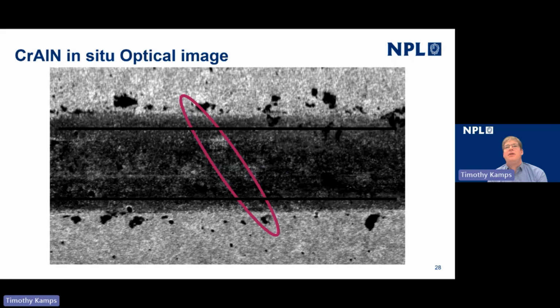And in some cases, it may not be of interest that the coatings failed in such a localized way, although it may be an indicator that it's about to wear catastrophically and give occasion to take the system offline. And in fact, that's what happened in this case. A couple of passes later, the coating began to delaminate from the ASP23 substrate and was peeled off from the surface, resulting in a very large amount of the coating becoming liberated.